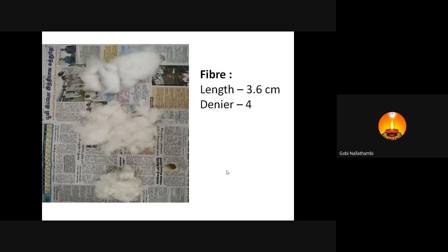Then these are recycled fibers. We obtained them from Tirupur. There are 2 or 3 companies producing recycled PET fibers nearby Tirupur. We bought some amount of fibers. The length of the fiber is 36 mm and the denier is 4. Denier is the mass per unit length of the material. So the thickness and length may vary depending on the denier. It is one of the important parameters which influences the property of the composite. So here we used 4 denier filament and 36 mm length fiber.